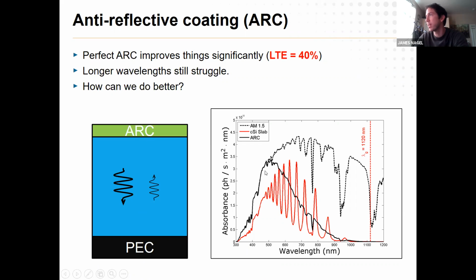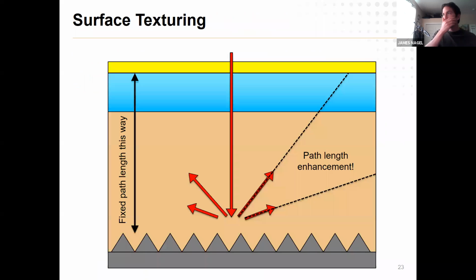So for very short wavelengths, I'm getting almost perfect absorption. Then you see how it splits around 500-ish nanometers, where all of a sudden I'm not absorbing super well. It gets worse and worse and worse as I go longer in wavelengths. Even so, I still get a good improvement. My light trapping efficiency went up from 27% to 40%. But I still need some way to trap all of those longer wavelength photons. So what can we do to make up that difference?